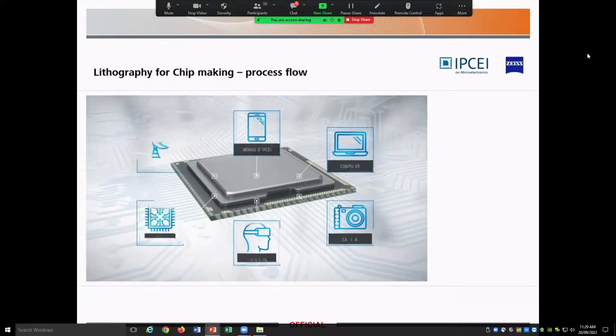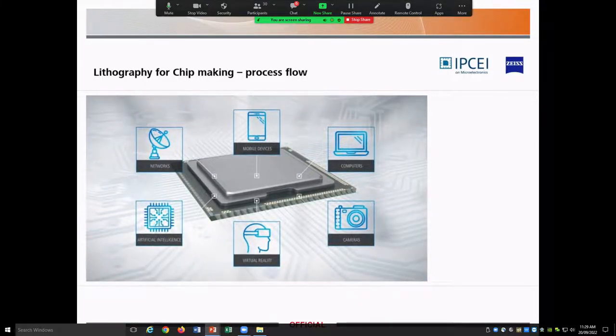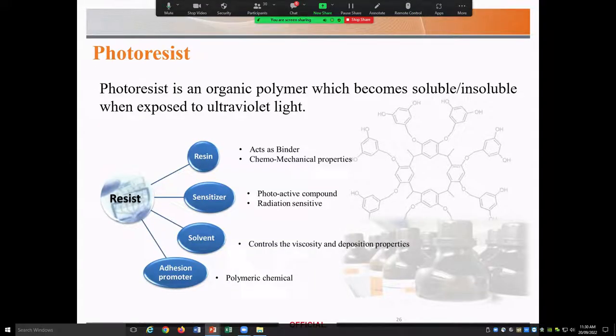So now that we know how these can be used, let's see what we need for our photolithography process. For the lithography process, we need photoresist and photomask. Photoresist is an organic polymer which becomes soluble or insoluble when exposed to UV light. It has some photosensitive compound whose properties allow us to transfer the image. And also it has resin and solvent to control the viscosity and the deposition properties.